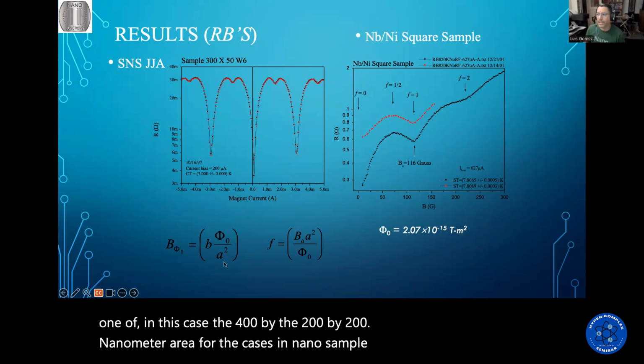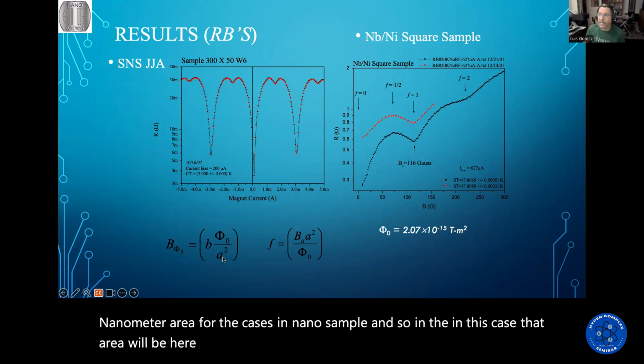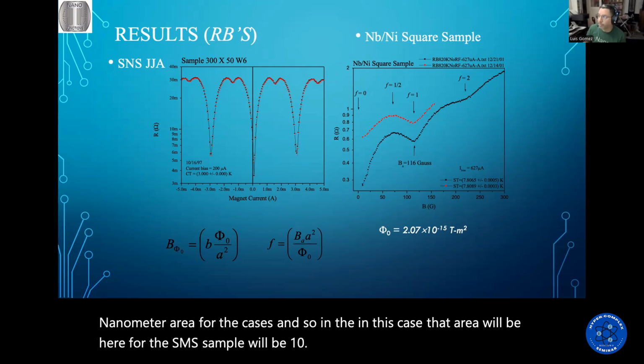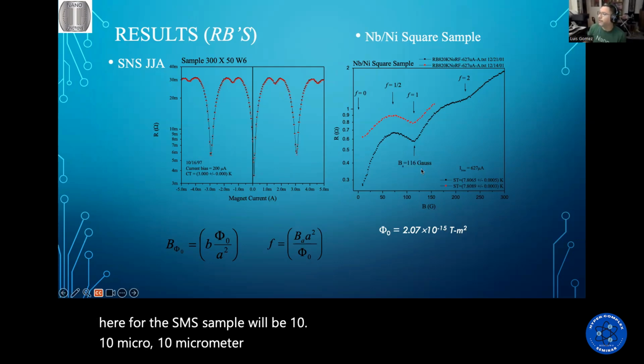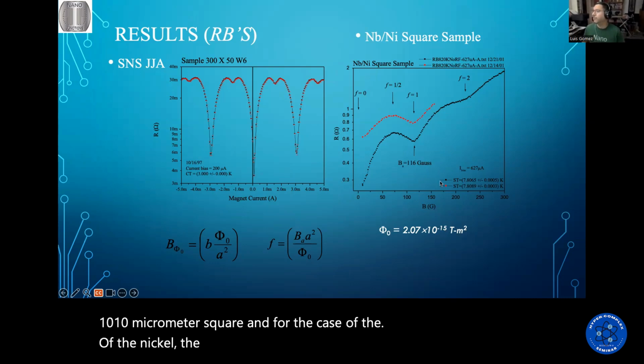So in this case, that area will be here. For the S-N-S sample it will be 10 micrometers square, and for the niobium nickel sample it will be 200 by 200 nanometers.